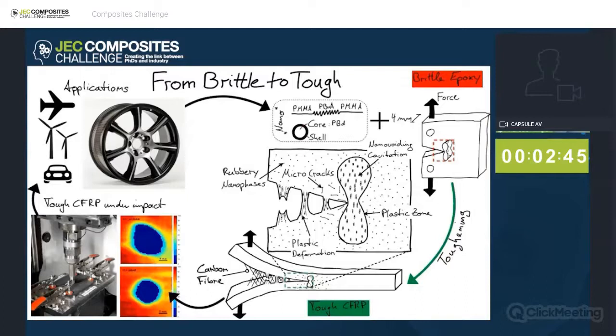What you do with these samples is you take those polymers, put them into your resin, and then during the curing process, these macromolecules phase separate into your obstacles, and then the crack can interact with them. So I focused on a bottom-up approach. I started first examining the phase separation process in our relatively complex resin system, which usually contains a resin, a hardener, and an accelerator.